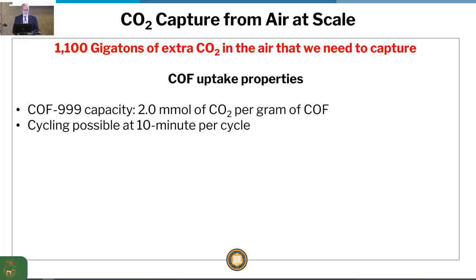Okay, let's say I have COF 999. We just improved it to 2 millimole of CO2 per gram of COF. We can improve it more. We're only using around 20% of the amines, so potentially we might be able to double this, triple this. There's capacity for tripling this.